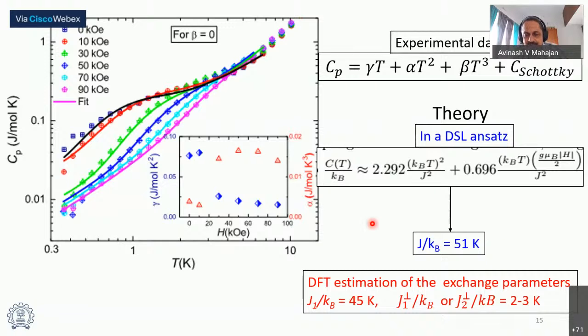Okay, note that our experimental number based on the bulk susceptibility is also about that, about 50K. Then, in addition to this, DFT estimation of the exchange parameters also gives a similar number. So everything from two kinds of theory and experiment seem to be consistently explaining this based on exchange coupling of the order of 50K between the nearest neighbors. DFT also gives a small coupling between the next nearest neighbors, either within the plane or between the planes. And so that explains the essential 2D nature of this system.